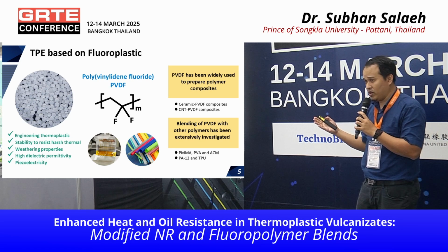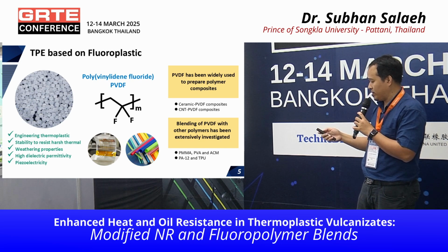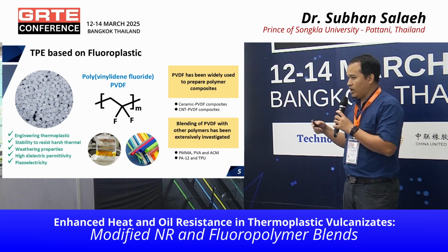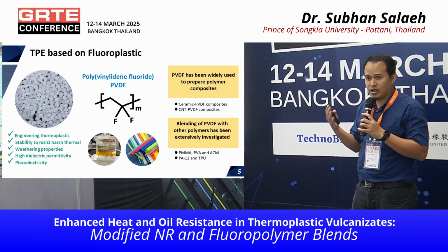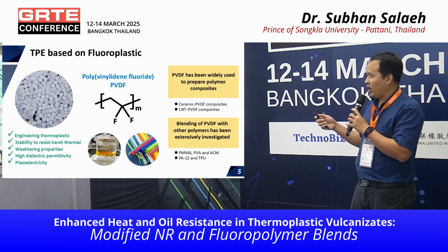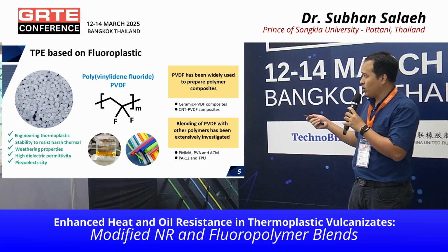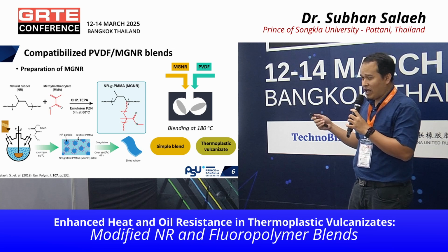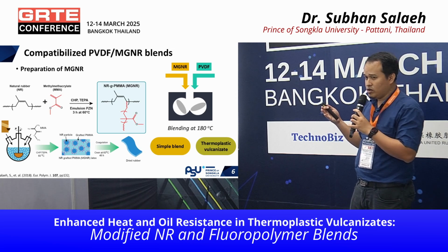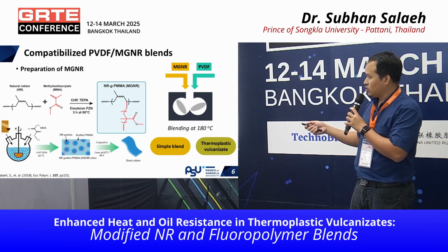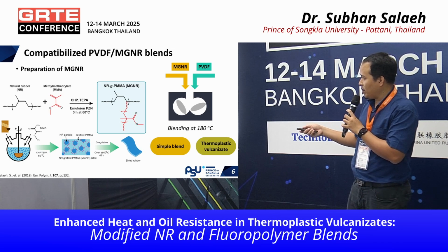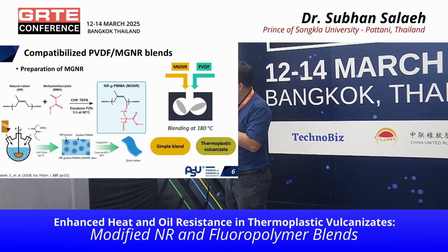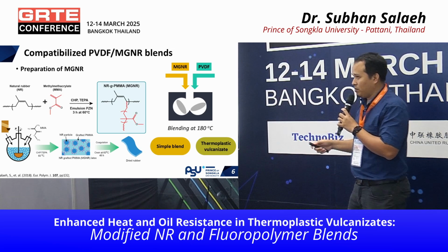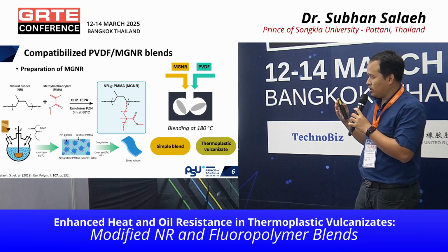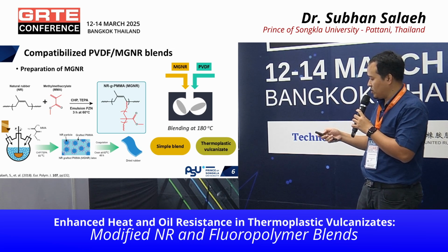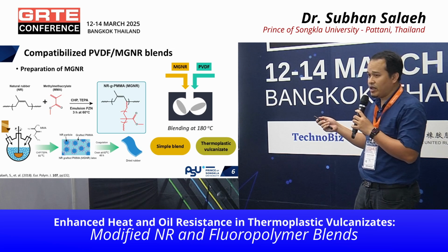Therefore, it can be used for various types of composite and blend. It can be blended with polyamide, PMMA, and acrylic rubber. In order to blend with natural rubber, we modify natural rubber with methyl methacrylate or polymethyl methacrylate. We graft polymethyl methacrylate onto natural rubber using emulsion polymerization, so we have a PMMA group here. This PMMA group will exhibit good interaction with the PVDF.